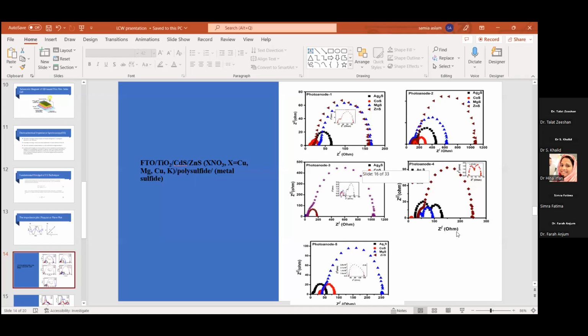So what these Nyquist plots simply explain here, since the impedance is a complex number, is represented by a circle, which should definitely be an ideal circle. But here, this circle is not ideal. Rather, its center is shifted, and it is a semicircle, and somehow this circle is suppressed, which means that the width of this circle is indicating a superposition of various interfaces present in the cell. It means that one semicircle ideally should represent one interface. So if there is a suppressed semicircle, it means that it is being represented by different interfaces.